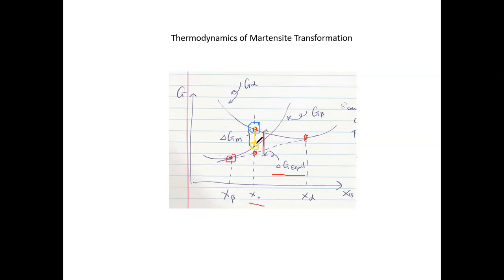Well, this means that everything gets stuck, right? Because you freeze the system to a very low temperature, so the atoms are not moving. This is fine, right? I don't have to change composition. I can have my alpha phase and the beta phase have the same composition. All I need is a change of crystal structure. If I can actually have the change of crystal structure with the same composition from the alpha branch to the beta branch, this also allows me to decrease the free energy a lot, right? Not to the best I can, but still can give at least a reduction of free energy by this delta Gm, where M indicates the martensitic transformation. Does this make sense to everyone?